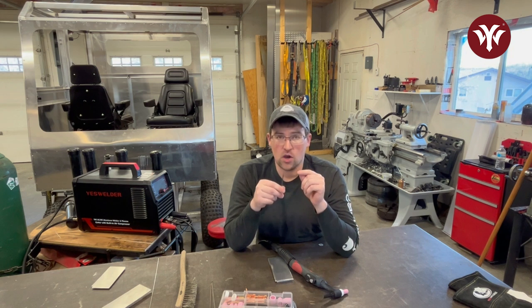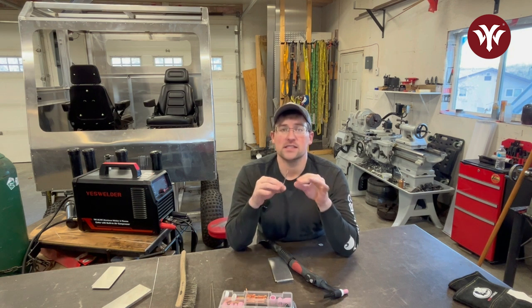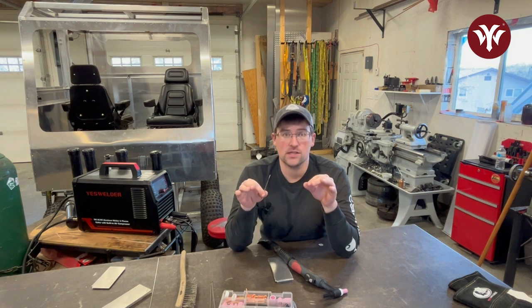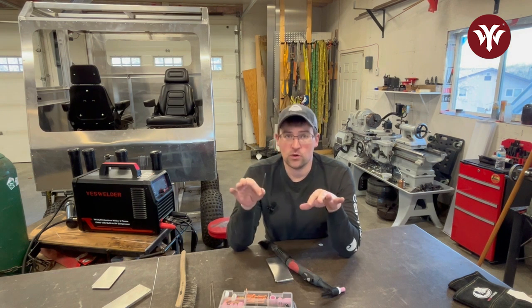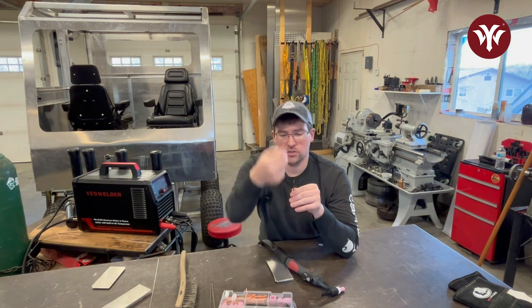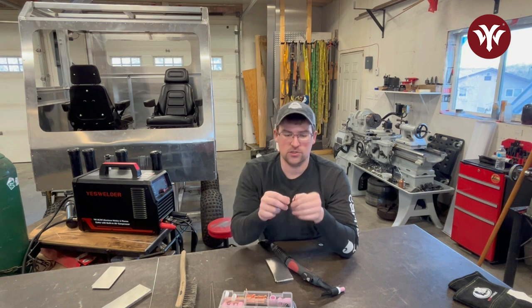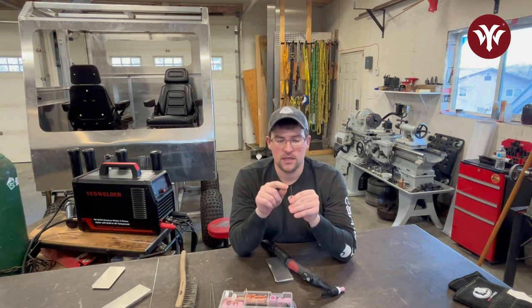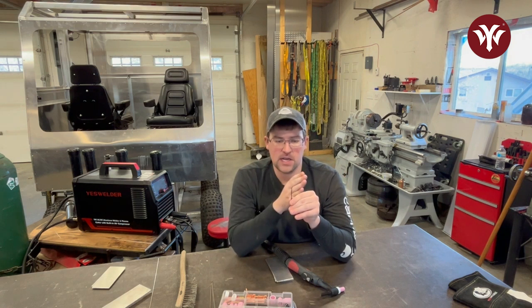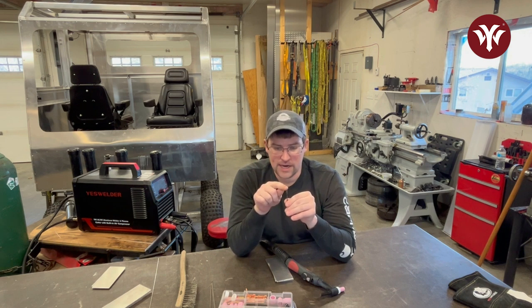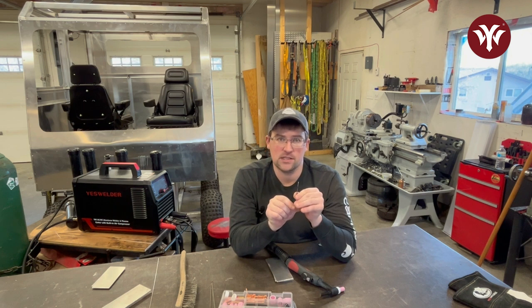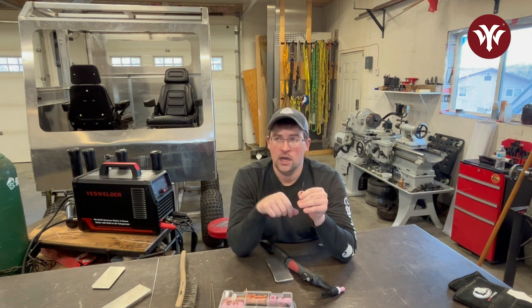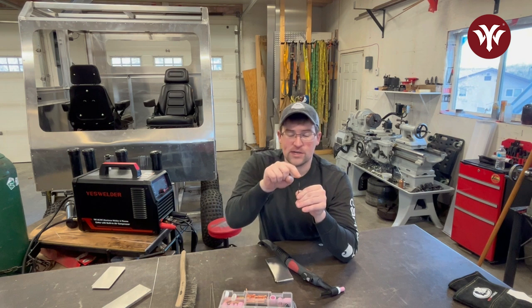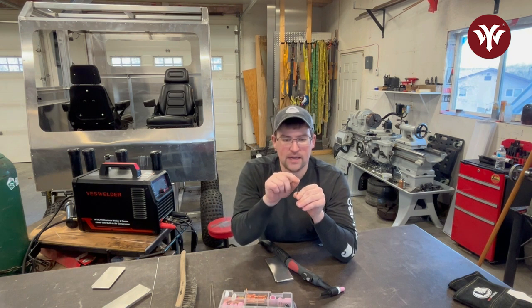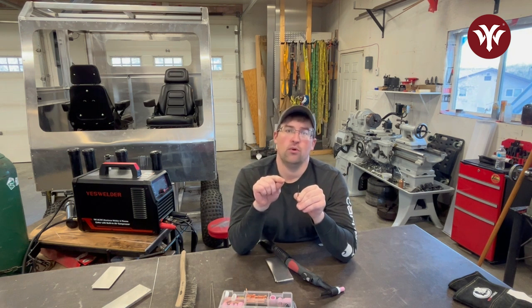When you're welding aluminum, it's all about clean, clean, and clean. You want to have as little contaminants as possible, and every step of the process is about getting those contaminants out of there. So use a dedicated stone, and grind parallel to the tungsten itself. If you're using different size tungstens, I always grind my taper to about 2 to 3 times the diameter of my tungsten. So if I'm using 3/32, I would go with about a 3/16 taper, and I have always used a slightly blunted point.